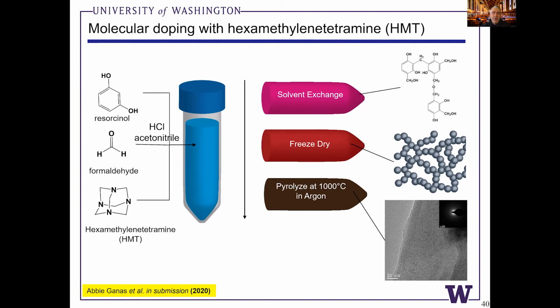that we just cannot get rid of. But we can at least try to add more nitrogen to the material and control the addition of nitrogen. So we started with this species, hexamethylenetetramine. This is an interesting molecule that looks a lot like a B center in diamond. If you replace 4 carbon atoms around a vacancy in a diamond, this is the definition of the B center. And we would like to control at least this concentration of nitrogen.